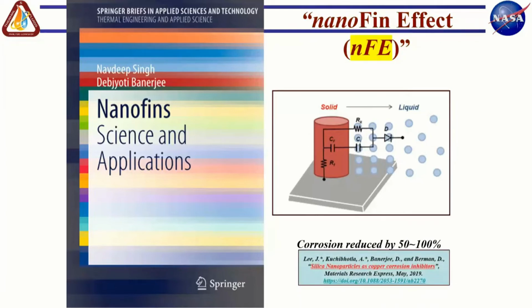So once we had this insight, we came up with this monograph, which is basically 70% of Navdeep Singh's PhD thesis. And then subsequently, we did a project with GE, where GE was interested in figuring out how much erosion or corrosion is caused by these nanoparticles as they flow in a conduit. And again, we found that instead of higher erosion, the precipitated nanoparticles actually reduce corrosion by anywhere between 50 to 100%. And this was work we did in collaboration with a materials scientist, Dr. Berman, at University of North Texas, and we published this work a few years ago.